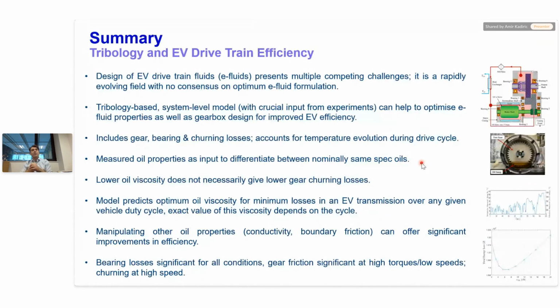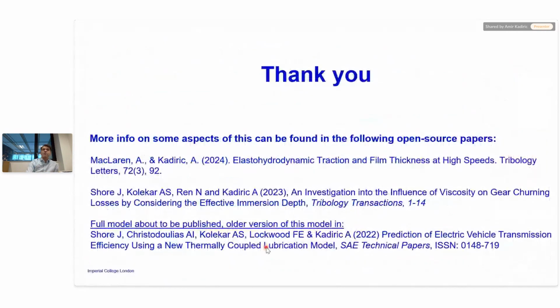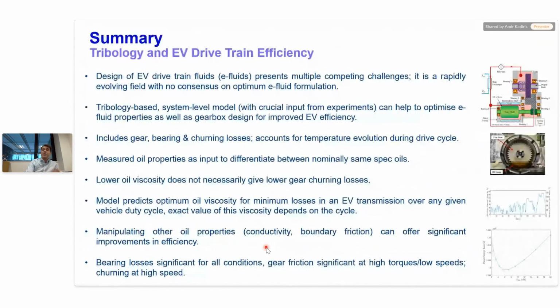The low viscosity is not necessarily a good thing for churning losses. There appears to be no need to go to ultra-low viscosities, and I think the world is slowly realizing that. And manipulating some of the other properties, I showed you conductivity, for example, can have a significant effect. And overall, gear friction is significant at low speed, high torque conditions, bearing losses in the middle range and at high speeds, and gear churning only at high speed conditions. So the optimum lies somewhere depending on what those conditions are and how you drive your vehicle.